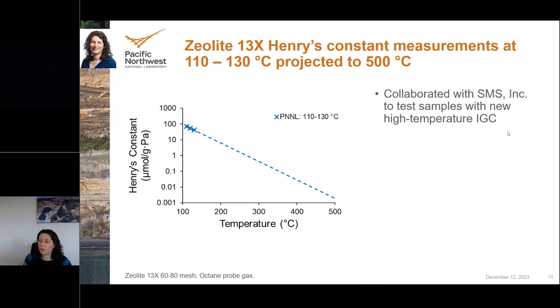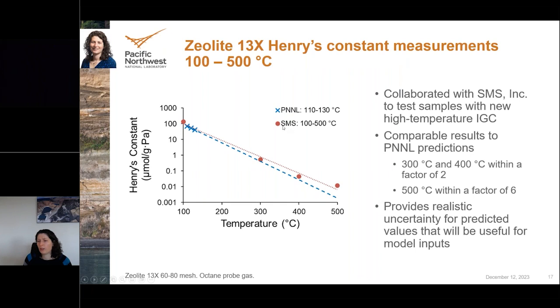So we collaborated with them and sent in a few test samples so that they could analyze them on high temperature IGC. And I have these results now showed in comparison. So with the SMS results, they're the red circles. They made measurements at 100 degrees, 300, 400, and 500. And then we have the dashed lines just to see how the two results compare. And what's really exciting is that the high temperature results compare well with our PNNL predictions.